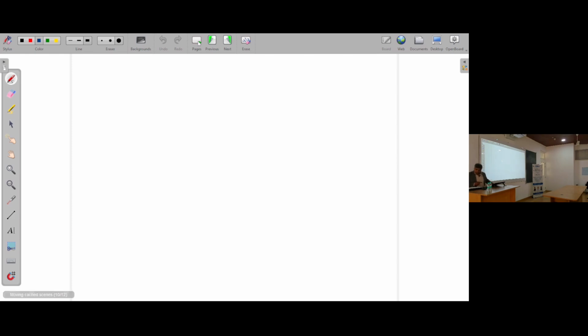Next page. So you would get simply something like the force because of the puddle is equal to P gas times h plus rho g h squared by 2.